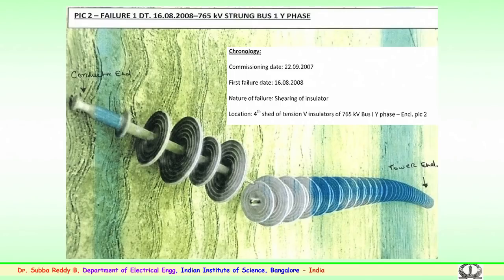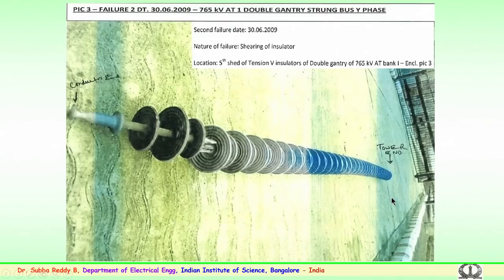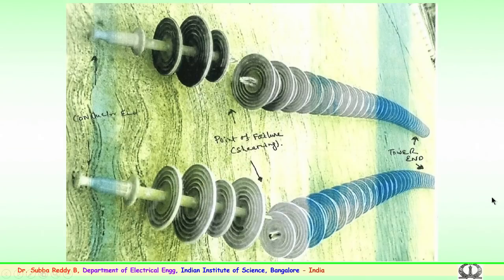There are some failures even in the country which are reported. I would like to explain this for the EHV insulators, where failures have happened at various junctions. You can see one of the failures is because of a brittle fracture that happened after the 5th or 4th shed here, in the country. Similarly, you can see the failure happened at the 3rd insulator, this is a polymeric insulator, where it has happened after the 3rd insulator. So, there are failures which have happened immediately after the stringing, within a year or so. This again is a very serious concern.